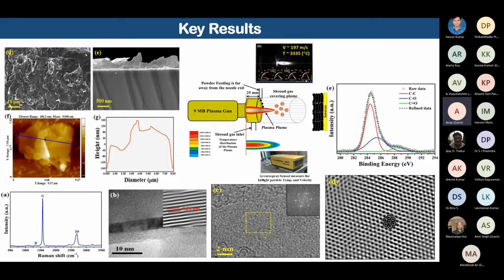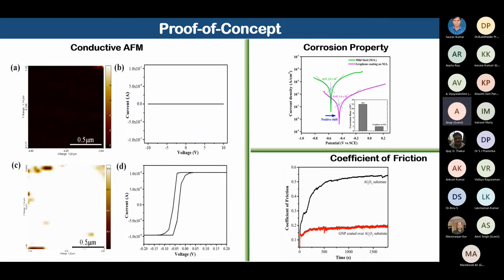Because of the inert atmosphere shroud, as well as the very high quenching rate. We have also done the proof of concept in the conductive AFM. You can see here on the left-hand side, image A is only the alumina substrate, and we know that alumina is an insulator. So that is why for the entire range of the voltage, you can see the current is almost 0.